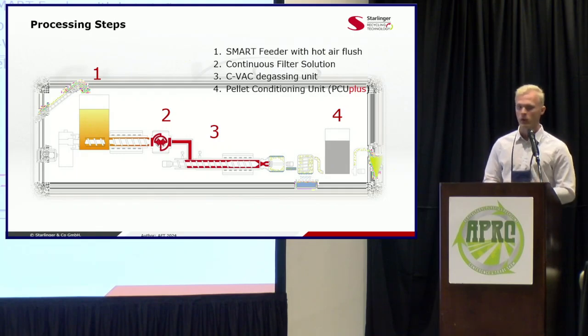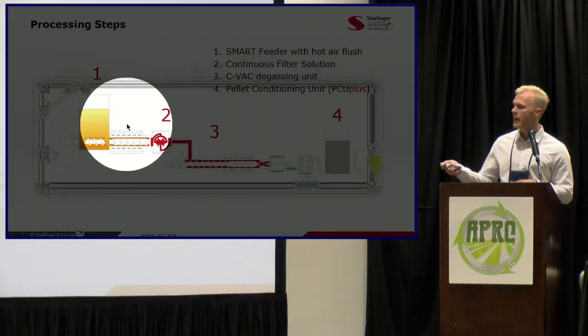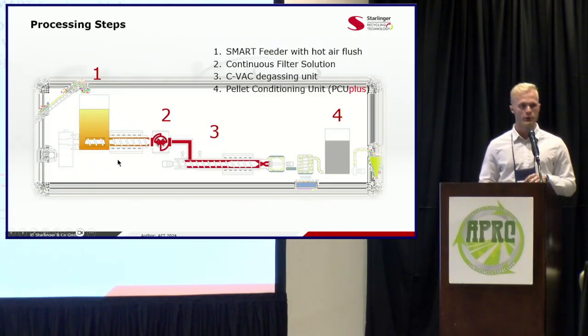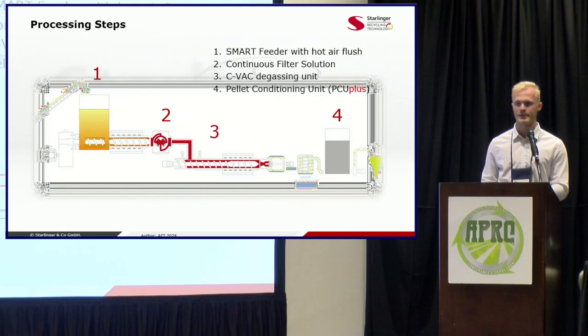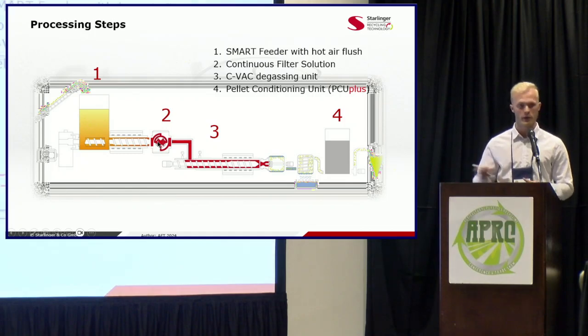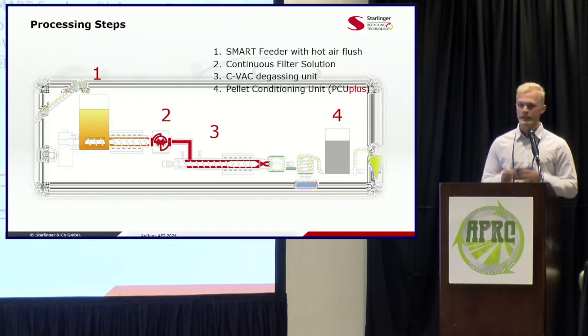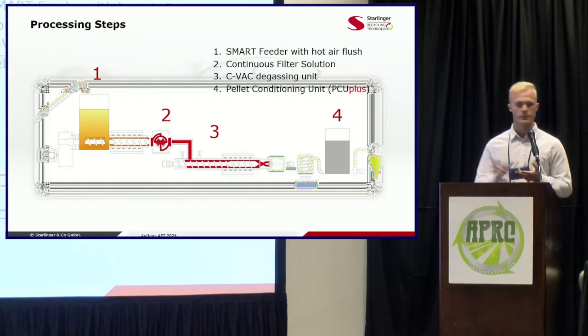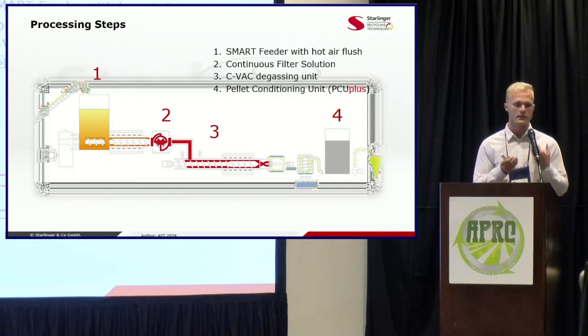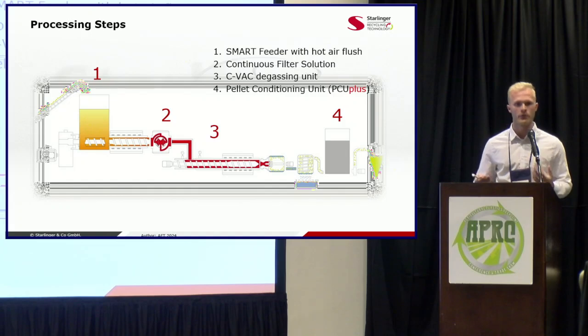An important thing to also note is that with this setup, we do not have a degassing port in the first extruder. So we're a unique manufacturer in that we split up the first extrusion screw and the second extrusion screw, which focuses just on degassing. This ensures that the continuous filter solution of your choice, which we often recommend Fimic in this case, can continue to catch those contaminants, such as the wood, such as the organics, that will actually off-gas on the filter screen. So if you have degassing prior to the filter, you're still going to have issues downstream with inclusions in your pellet, because as that contaminant sits on the filter screen, degassing had already occurred. So that's going to be present in your pellet and is going to cause issues downstream.